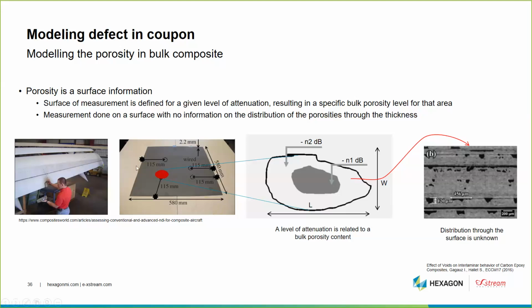So we have only that information on the surface, because we don't systematically cut the plate just to verify the level of porosity. We just know where the porosity is suspected to be. When we detect an area with an attenuation of the ultrasound, we give a kind of normalization of that area. We define a rectangle, and for all the material under this area, we consider that we have the presence of porosity. But we don't have any information on the distribution of this porosity through the thickness. Unless we cut the coupon again, we have no way to identify where the porosity is located through the thickness. That's why we made the assumption in the software that all the plies under this surface are concerned by the porosity. It's a way to remain conservative.